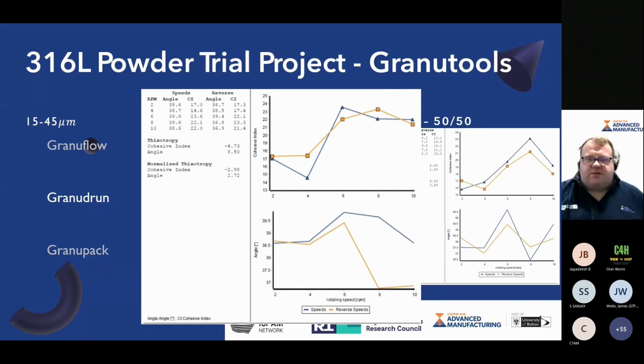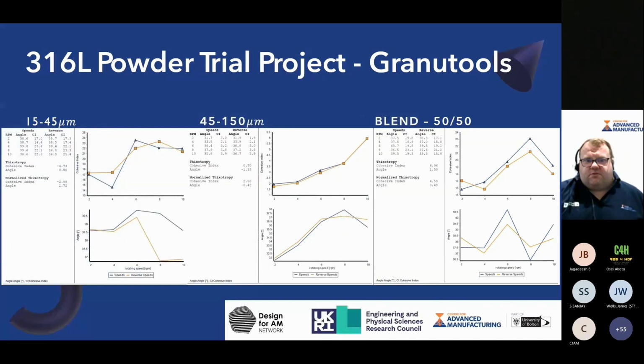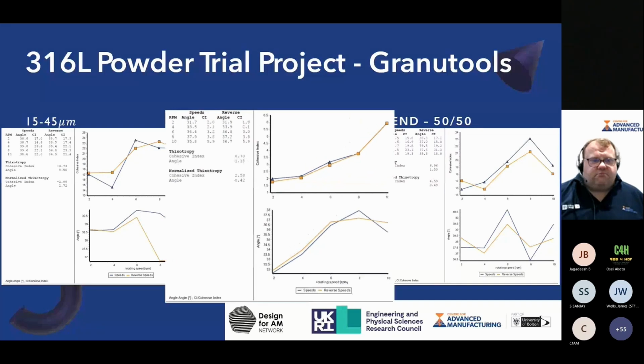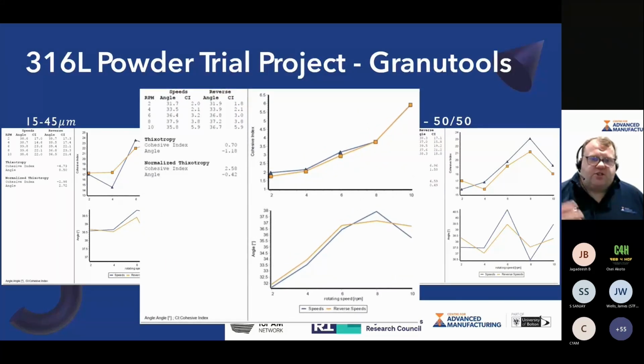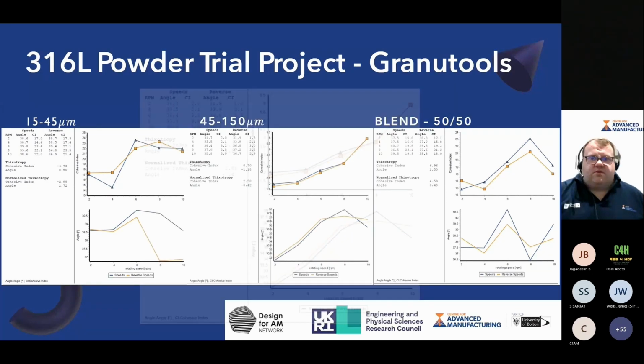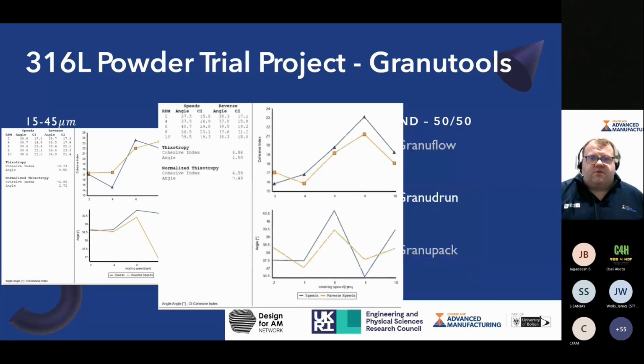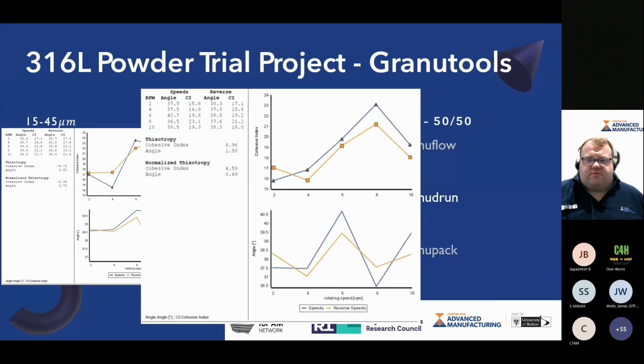We also see some differences between the speeds on the way up to the reverse speeds. Quite a sticky powder, I would say, quite surprisingly. Our Scalmalloy tests recently were very, very sticky, and that shows quite clearly in terms of the large powder. Relatively predictable, let's say. So predictability is a nice word to be able to use with metal AM. The blended powder has the best of both worlds. There's some predictability, but some quite strange behavior in terms of the way that the powder was starting to act as the speeds increased up towards 10 RPM.